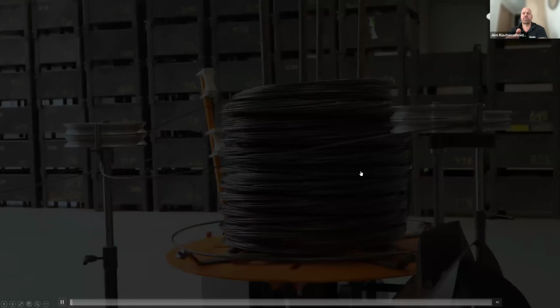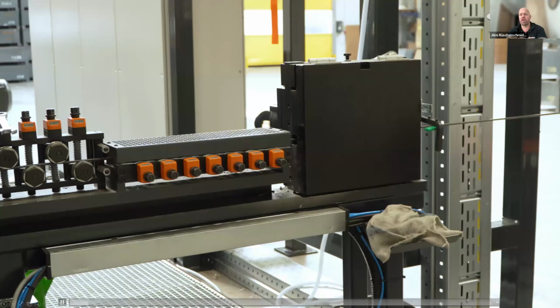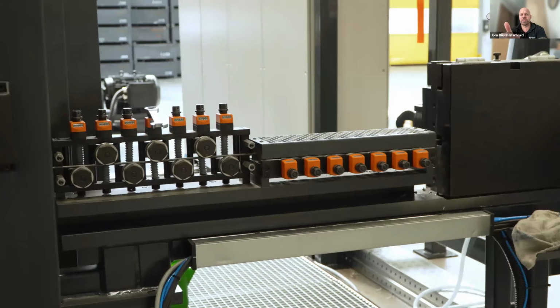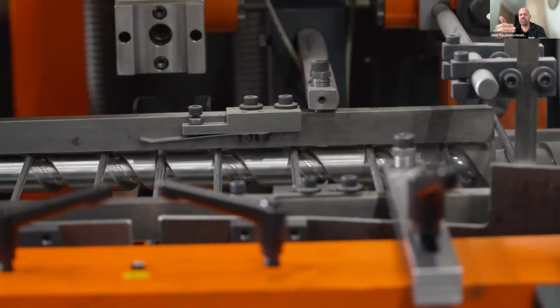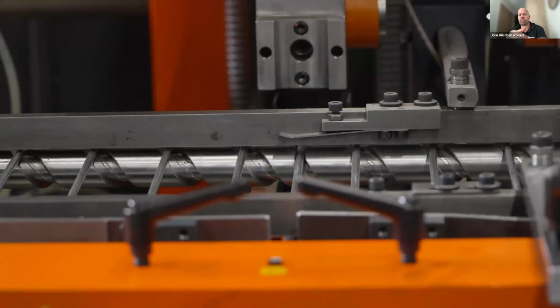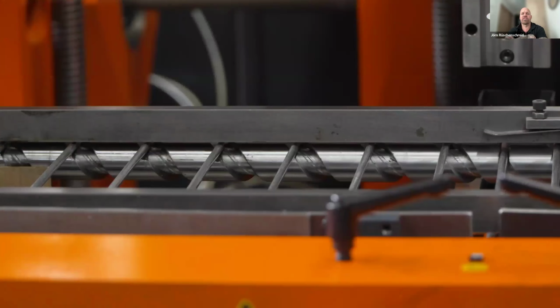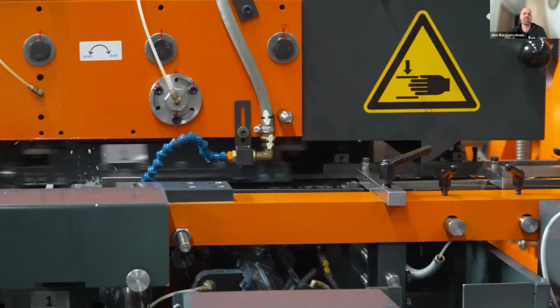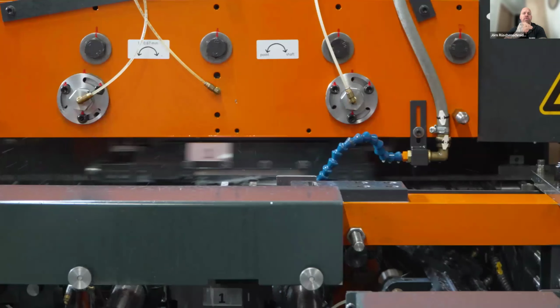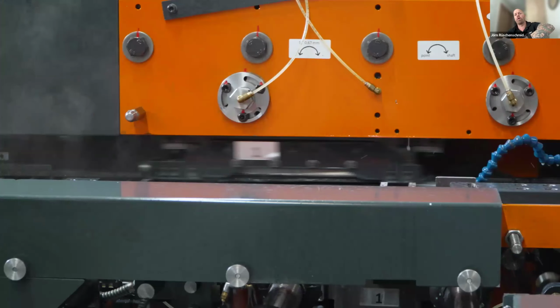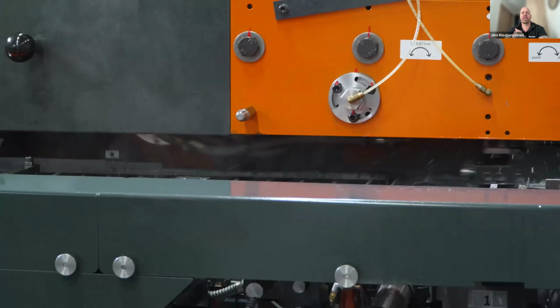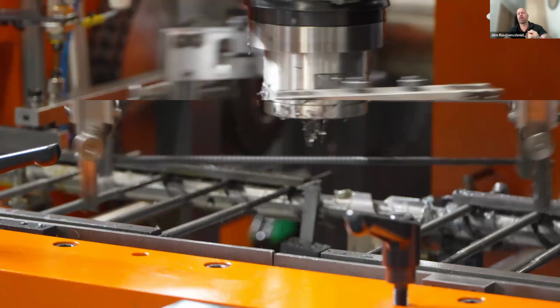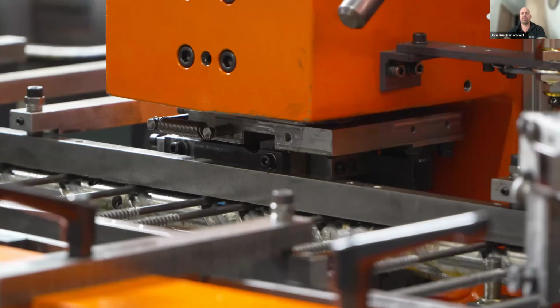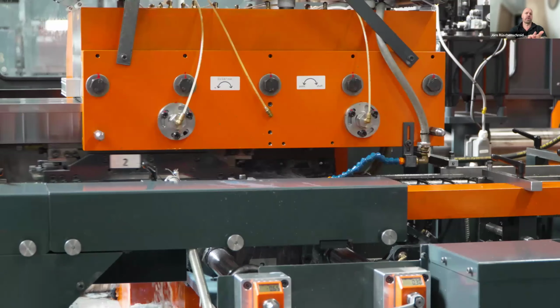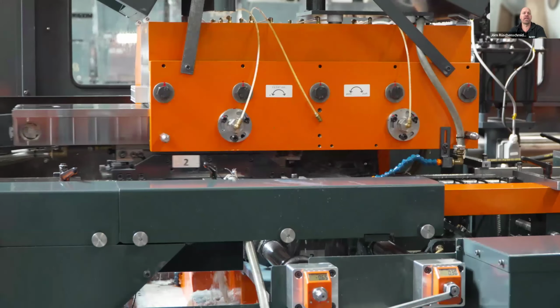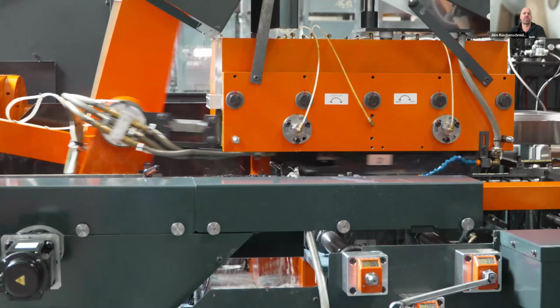So here you see it's the same procedure. We got the raw wire on a cone. The wire is stretched and straightened. Then the wire is cut into length. Then we start forging the head in two steps as we do for partially threaded. There you see the forging pressure. Then we roll the first thread. A robot turns the screw so that the point which faces to us now faces to the back of the machine. And then a second thread roll will roll the remaining 200 millimeters of thread on top of the machine.